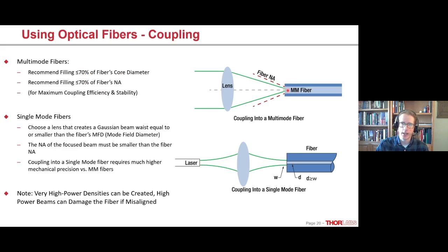And so if you put it behind, or even in front, and you have the beam diverge a little bit or be not quite focused at this end face, then you can have the lowest power density possible that still fits inside the fiber's core. And thereby it's a safer way to work with high power without sacrificing coupling efficiency into the fiber.